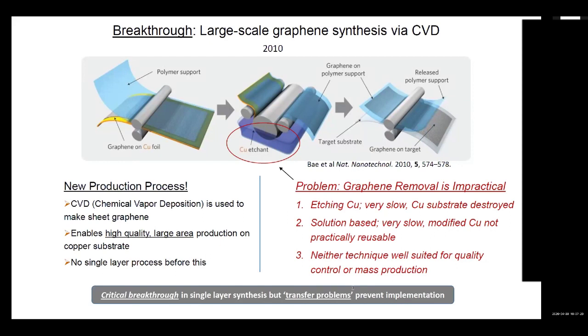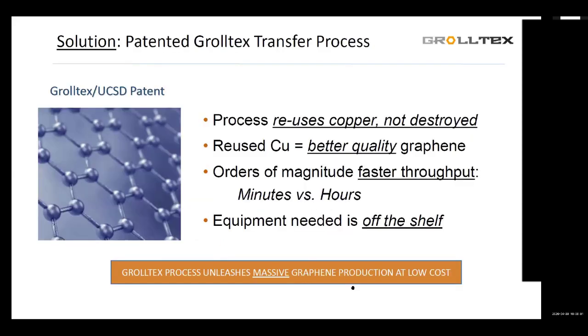And one of the big reasons we believe is the next step down the line, that's transfer. When you're making your high quality CVD graphene on copper, the next step down the line is getting your graphene off the copper. Today, the state of the art seems to be acid etching copper. That's expensive, it's slow. We don't think that's the way forward. And so Dr. Zaretsky spent a lot of time thinking about this and came up with what we think is a very important piece of the puzzle in advancing CVD graphene proliferation, and that's solving this transfer issue.